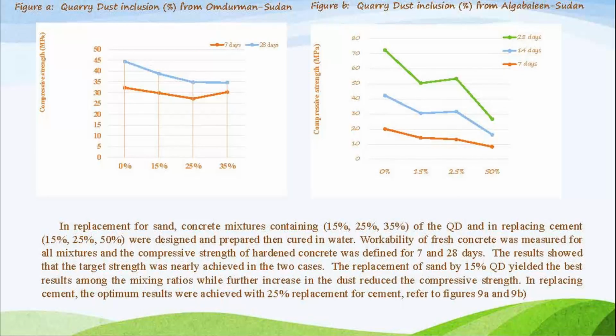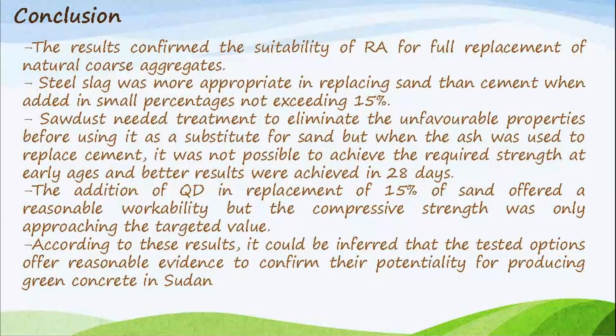Then the workability of fresh concrete was measured for all mixes, and compressive strength. The replacement of the sand by 15% QD gave the best result, and for the replacement of the cement about 25%. The result confirms the suitability of recycled aggregate for full replacement of natural coarse aggregate. Steel slag was more appropriate in replacing sand than cement when added in a small percentage, not exceeding 15%.